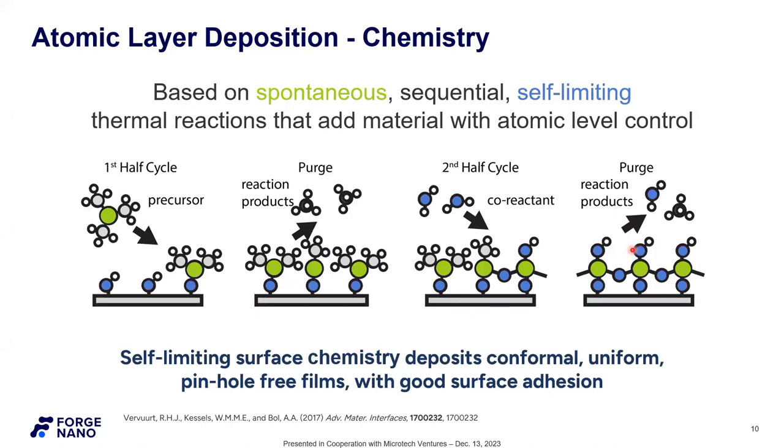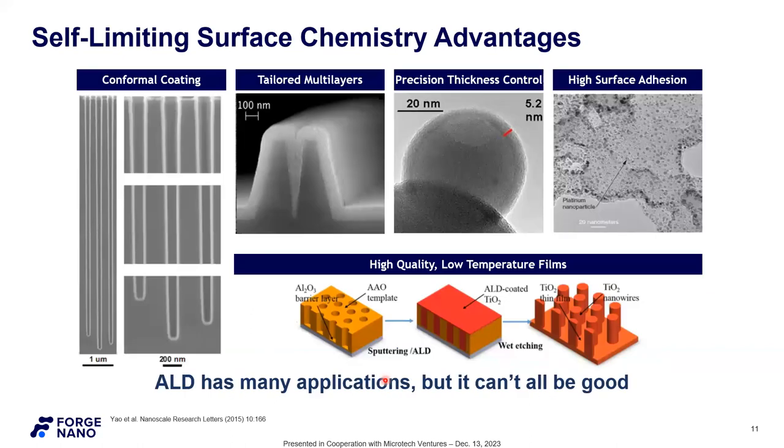So there are some very cool things that come out of this very simple schematic for ALD. I've listed them here at the bottom, but I actually prefer to talk about them in pictures because it's a little bit more intuitive for me. The first thing that comes out of the self-limiting nature is what we call conformality, or conformal coatings. I've already said it a couple of times, but anywhere that the ALD process gas can go, you will get a uniform coating of ALD film if you wait long enough. There's a bit of a caveat there, but it's quite important. Here I'm showing a 100-to-1 aspect ratio feature. It's coated with the same amount of ALD film at the top as it is at the bottom. Again, this is where people usually come to ALD for this behavior.